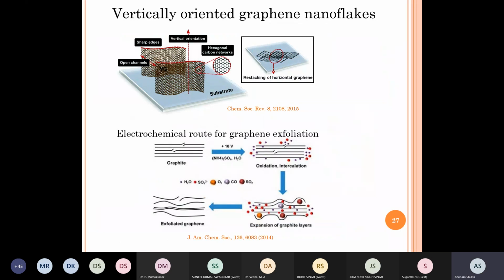So one of the things which have been explored here is to construct an electrode where one has vertically oriented graphene nanoflakes. So you have a conductive substrate and then somehow arrange graphene flakes which are vertically oriented so that they provide higher area. They should not be horizontally oriented as shown here, because if that happens, then a lot of the surface area of graphene is actually hidden in the stacking and is not available to electrolyte.